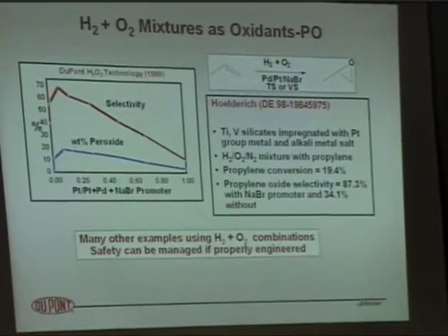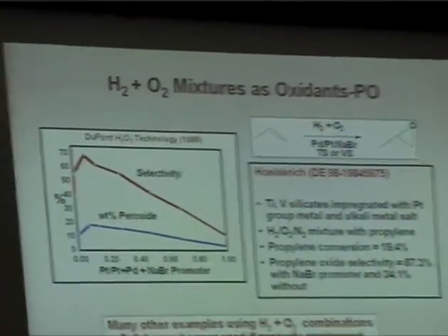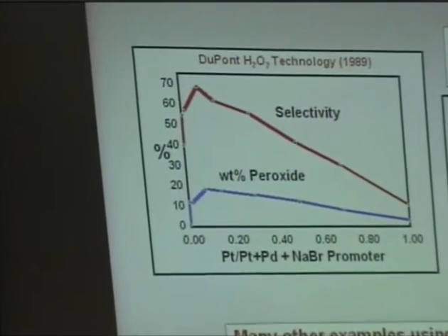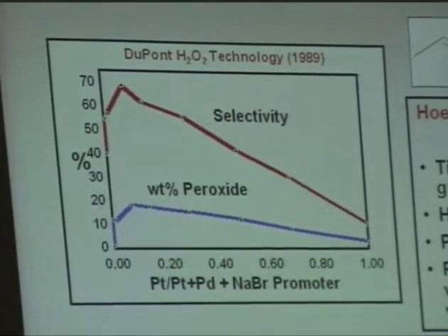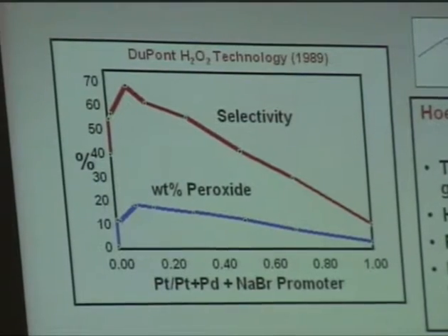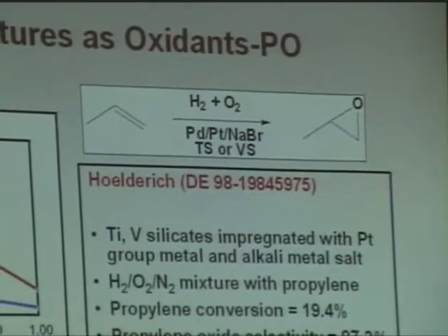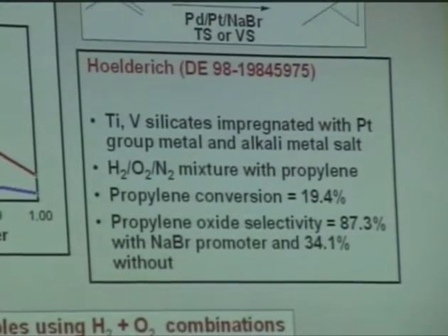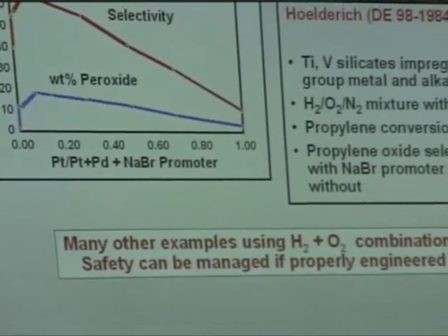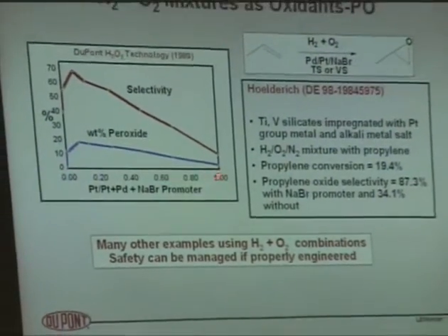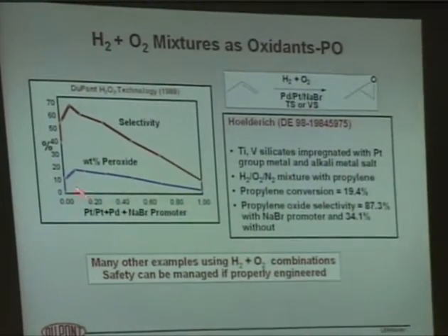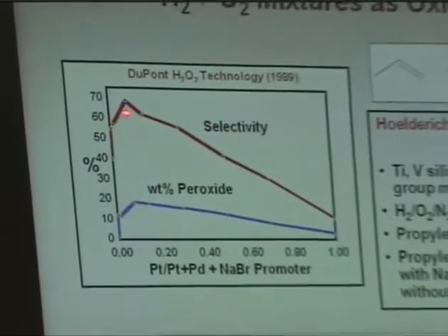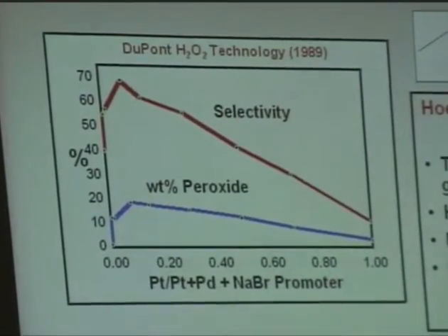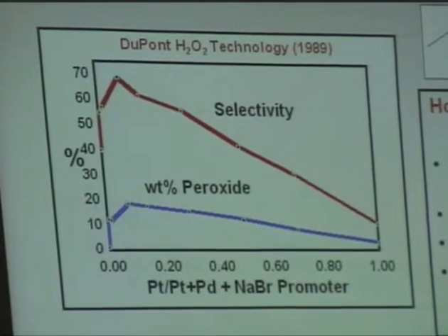Hydrogen-oxygen mixtures have been talked about for a long time. Extremely hazardous mixture to work with. Concentrate on this slide for the time being. We worked for nearly 20 years on combining hydrogen and oxygen directly to hydrogen peroxide. The best catalyst system that we came up with was a 10% palladium platinum combination catalyst. And shown here as you vary the palladium and platinum ratio, the best results we were able to get were about nearly 70% selectivity directly to hydrogen peroxide from hydrogen and oxygen.